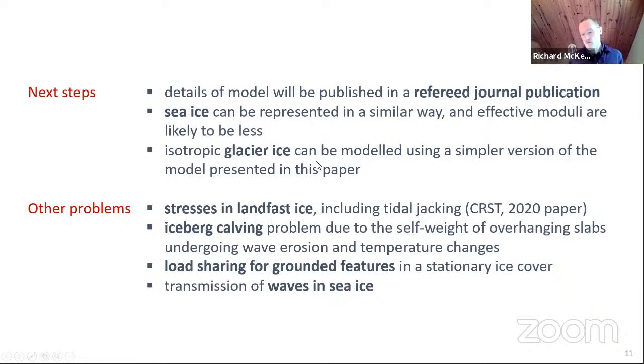Other problems that we've looked at: we did write a cold regions paper where we looked at stresses in landfast ice, both due to wind stress over the surface and tidal jacking from shore. We've done some preliminary, unpublished work on the iceberg calving problem. That is, if you have an overhanging beam of ice undergoing wave erosion, it's a continuous process where you have a temperature gradient within the ice. Most of the work being done on the iceberg calving problem uses an elastic assumption for ice behavior. We found that there is a viscoelastic effect, and that influences the maximum stresses that you actually see at the base of the overhang.